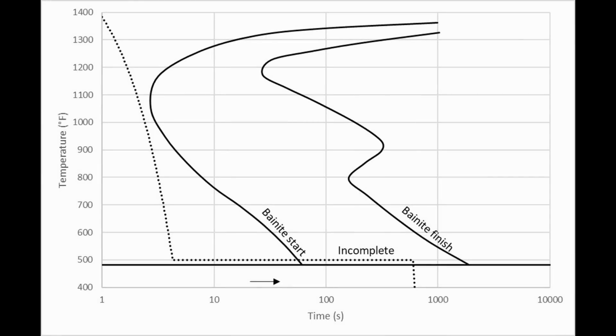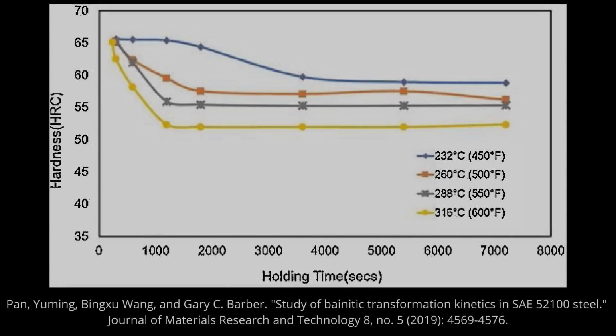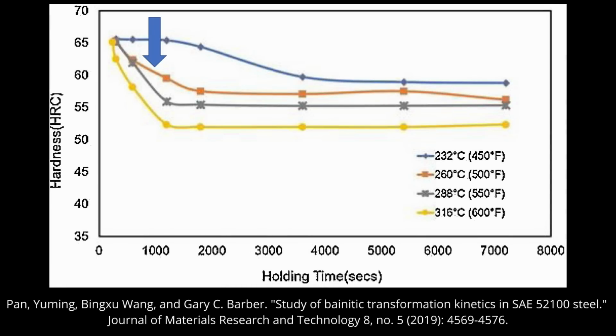So if we held for an intermediate period of time, like 1,000 seconds at 500 degrees, you would have some amount of bainite, and then when you air cooled, the rest of the steel would transform to martensite. And so you'd have an intermediate hardness value. Now, when they reach 2,000 seconds, which is about the same as what we saw on our TTT diagram, then the hardness was around 57 Rockwell, and with further holding time, the hardness was flat, meaning that likely no more bainite or only very small amounts of bainite formed.